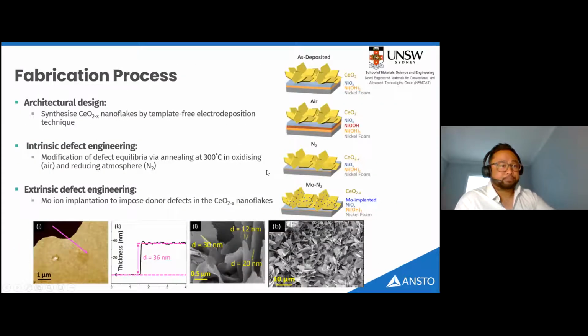Next slide, please. So the image on the right illustrates the fabrication process. Firstly, the architectural design component involves synthesis of the cerium oxide nanoflakes by a template-free electrodeposition technique at UNSW. Secondly, we modified the defect equilibria, intrinsic defects, by imposing annealing under oxidizing or reducing atmospheric conditions. That was done at UNSW. And then finally, we ion implanted the samples with molybdenum to incorporate extrinsic donor defects into the nanoflakes.